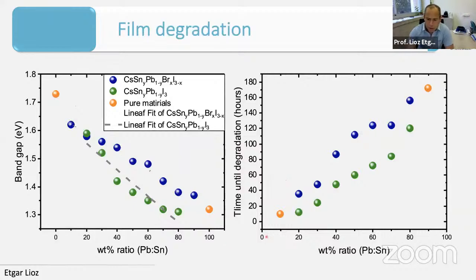In terms of stability, indeed, when you put more and more tin, and this is the time until degradation of the film under continuous illumination, you can see nicely that when you put more and more tin, the films survive outside without degradation. And this is amazing because when you take cesium lead iodide, after 2 minutes it goes yellow. And here, while you add in some tin, you can get a much more stable structure. So you get two benefits out of it. First, better stability. Second, a much narrower band gap. And these are two properties that you want.